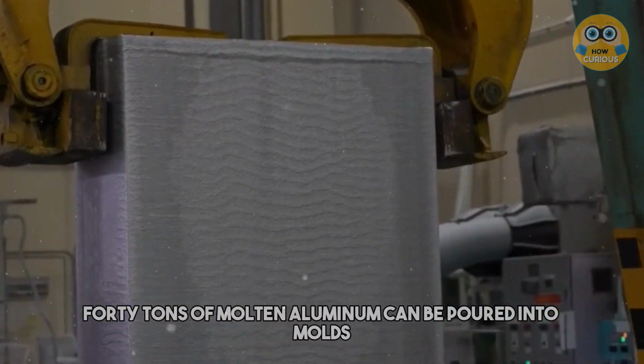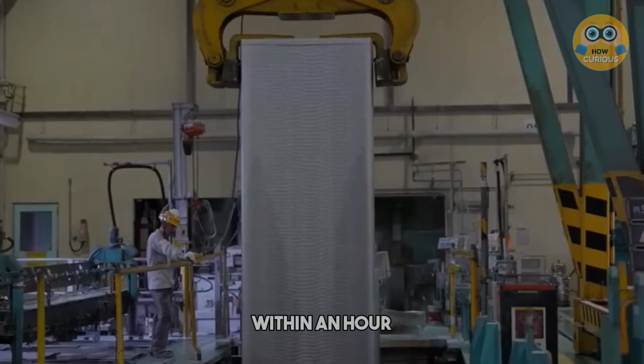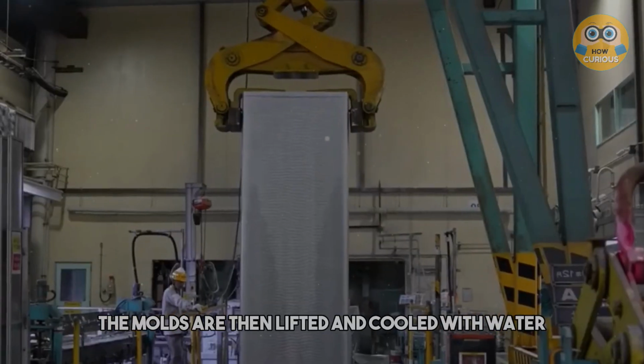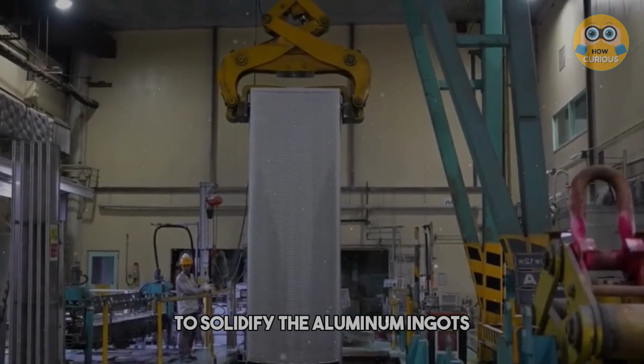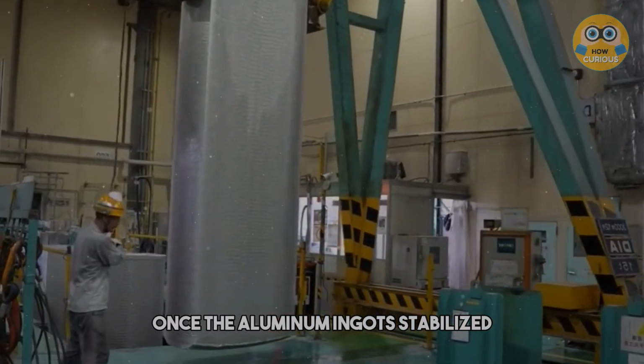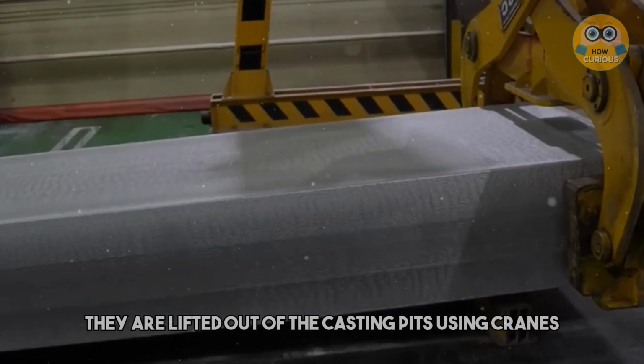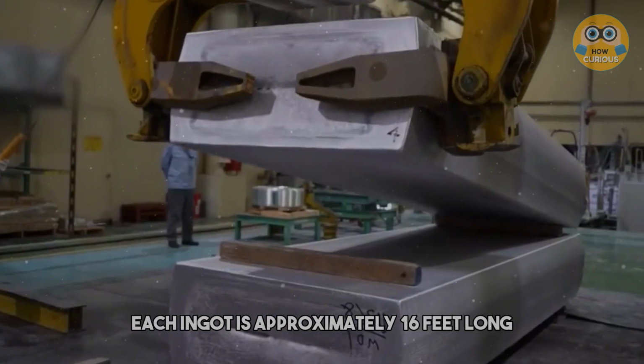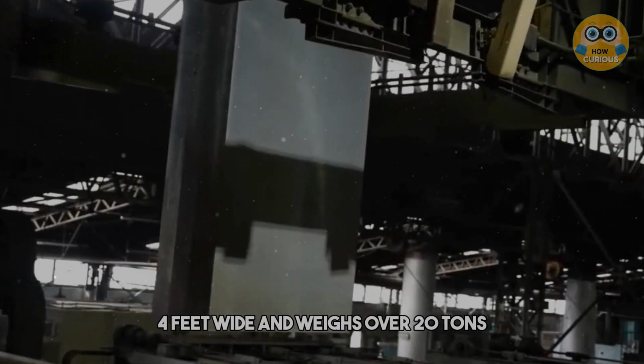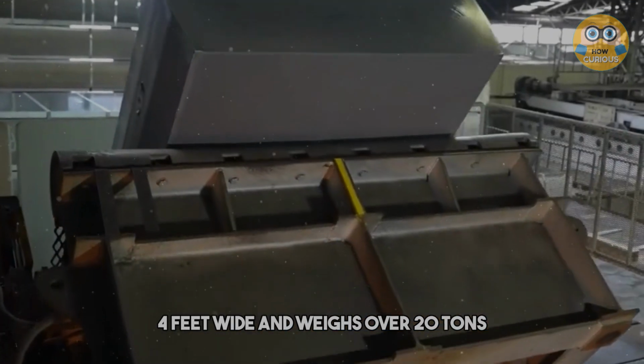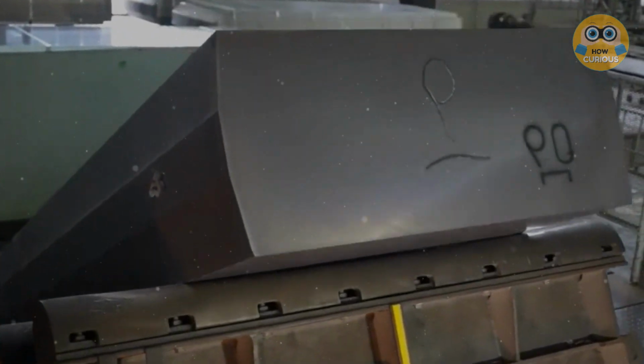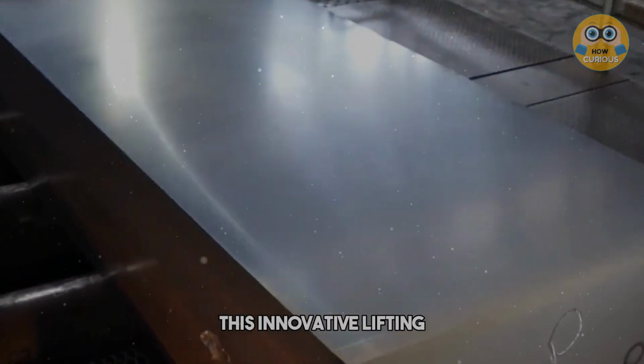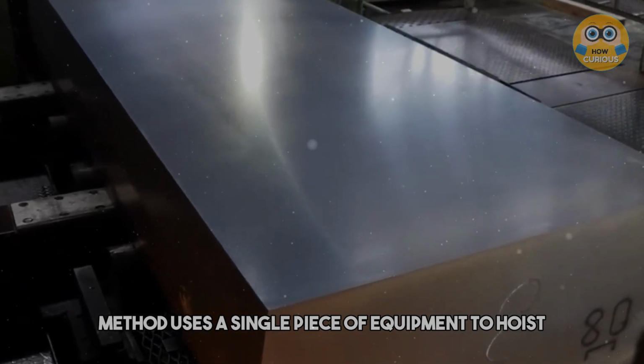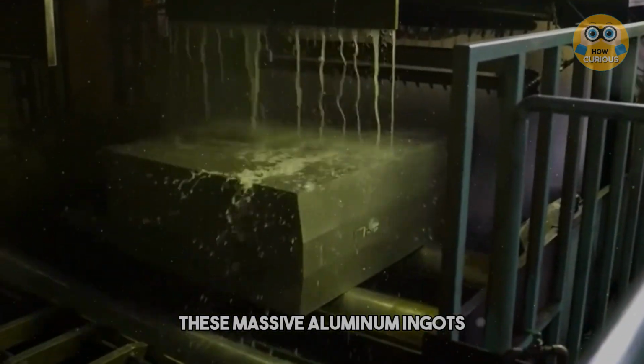40 tons of molten aluminum can be poured into molds within an hour. The molds are then lifted and cooled with water to solidify the aluminum ingots. Once the aluminum ingots stabilize, they are lifted out of the casting pits using cranes. Each ingot is approximately 16 feet long, 4 feet wide, and weighs over 20 tons. This innovative lifting method uses a single piece of equipment to hoist these massive aluminum ingots.